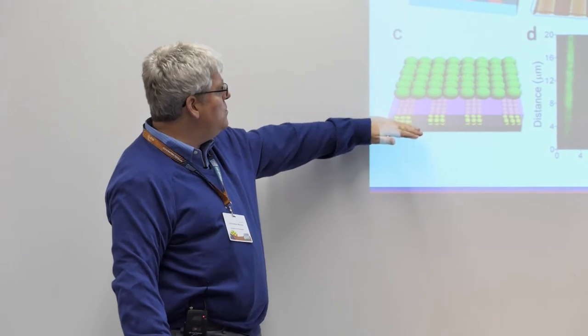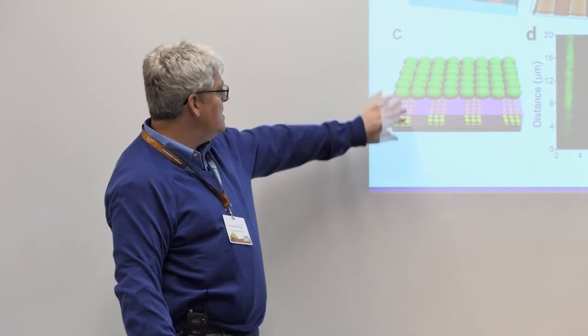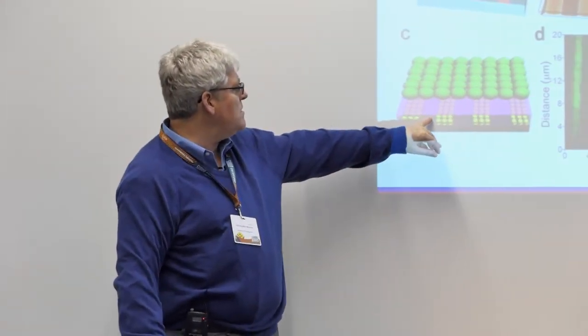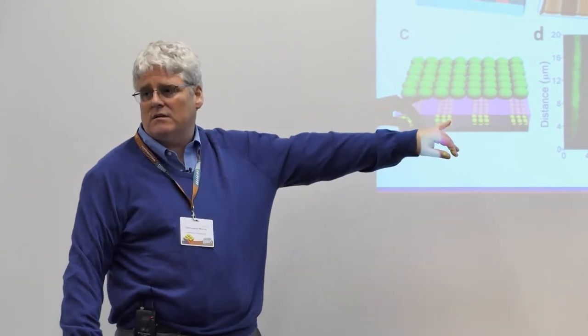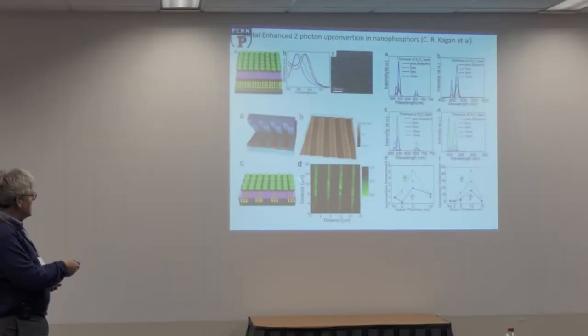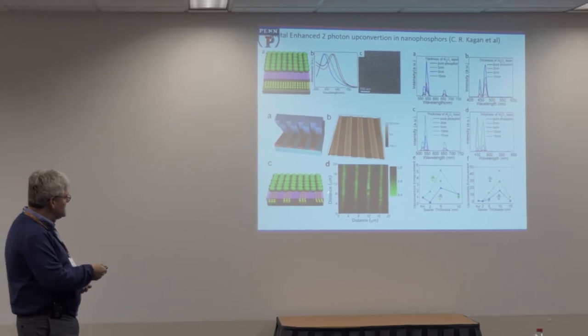resonators first. And so now you have a system where only the regions that are close to the resonator should see an enhancement in their fluorescence properties, while the regions that don't have an antenna should have the background signal of the original phosphor. So it helps you to get away from any risk that you have a poorly calibrated optical response, because the only source for this enhanced luminescence is the property of this increased luminescence